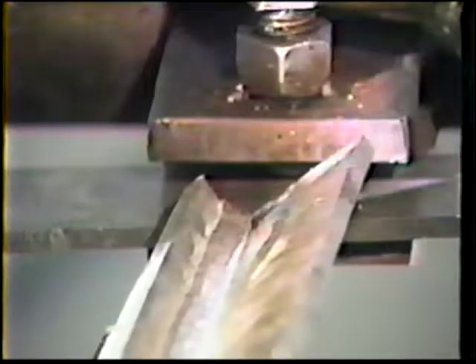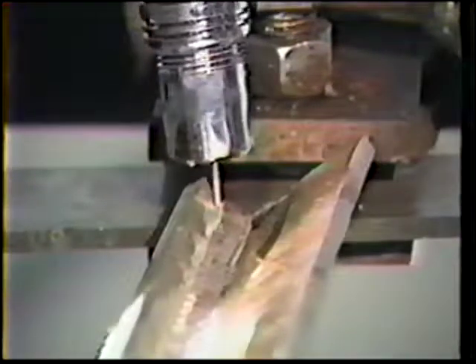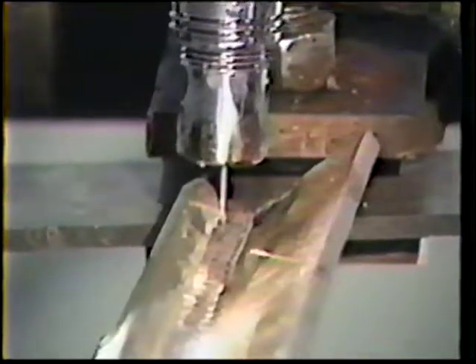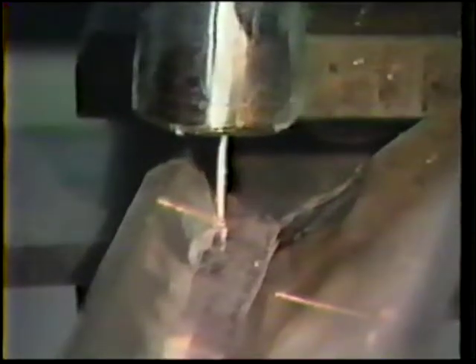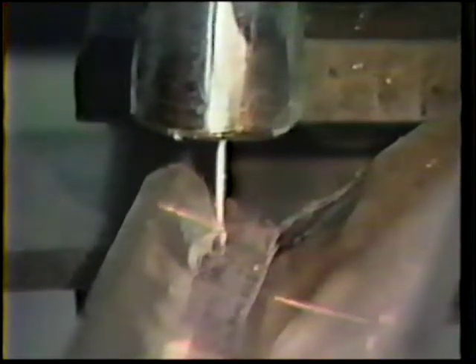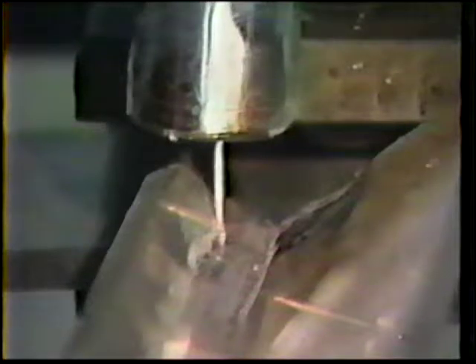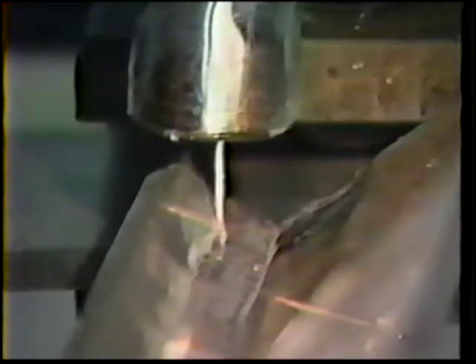Weld the first beads on all workpieces before beginning the second pass. For the second bead, position the gun with a 50 to 60 degree work angle, directing the electrode toward one toe of the root pass in order to overlap it about 2/3 of its width. The travel angle is the same as before. Move evenly along the joint with a slight weaving motion. Keep the wire slightly ahead of the puddle center and do not hesitate.